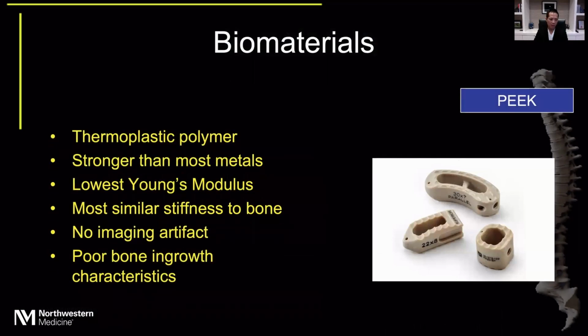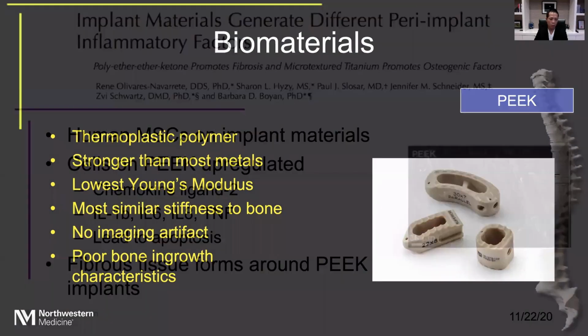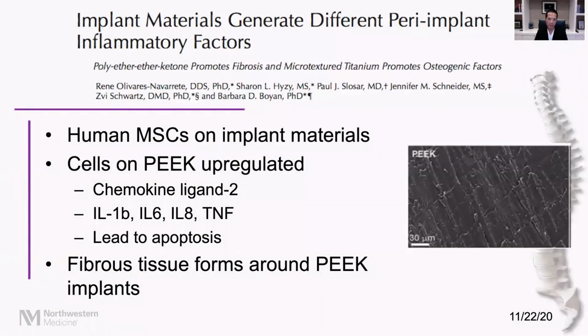Finally, PEEK is a thermoplastic polymer that is stronger than most metals, has the lowest Young's modulus, and has the most similar stiffness to bone. So if subsidence is an issue, PEEK as a material will inherently create less subsidence. There is no imaging artifact, but on the flip side, there are poor bone growth characteristics.